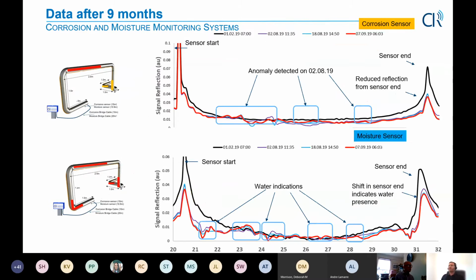Jumping to 9 months, after the monsoon season was over, corrosion was detected at multiple locations and water was indicated at multiple locations. Bear in mind, on the left-hand side, you see corrosion on the top and also mild corrosion somewhere at the bottom of the pipe, and moisture being stagnated at multiple locations. Some of them are where the corrosion is happening on the sensor, but some of them are elsewhere where in the future we will see corrosion.